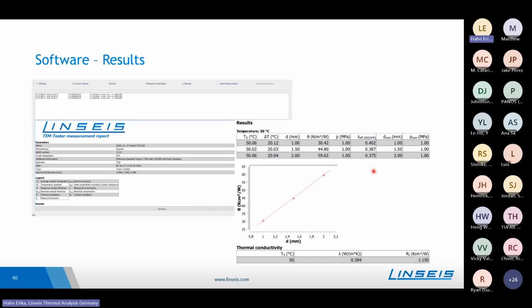And the effective thermal conductivity is calculated as well, which is basically just the sample thickness divided by the thermal impedance. But here you can directly see that this effective thermal conductivity varies. This is just due to the fact that this effective thermal conductivity still includes the contact resistance, so that one should rather have a look at the bottom of the report, where the conductivity is determined out of the inverse of the slope of the relation between the impedance and the sample thickness. So this is all done in the software, and one also will see then the contact resistance.